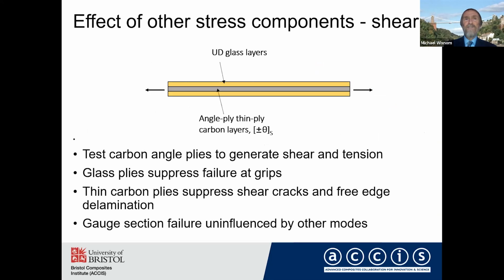We then go on to look at what about the effect of other stress components. And here, these results to me were quite surprising when we got them. So we wanted to use these test methods with good gauge section failures to look at the effect of other stress components. So in this case, we've got interaction of shear and tensile stress. What we've done is we put angle ply carbon in the middle here, and then use the glass on the outside. So the glass has got the same purpose of avoiding failure where we grip them, so we can get gauge section failures, but by using angle plies, we can get combinations of shear stress and tensile stress.